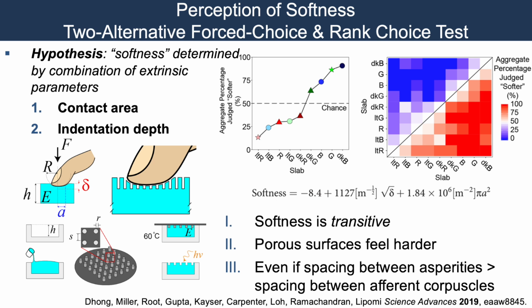There are a couple of different ways of judging how soft these materials are. In the first method, you can plot the aggregate percentage of the slabs that were judged soft. In this case, the dark blue circle, which has a certain contact area and indentation depth, a certain amount of surface coverage with these structures, as well as a certain thickness, is judged to be the softest most of the time.